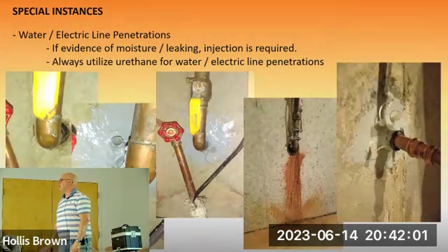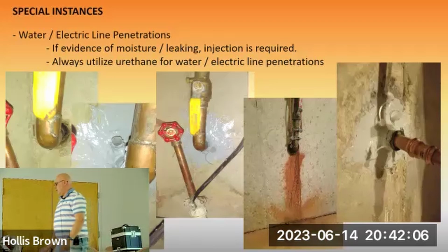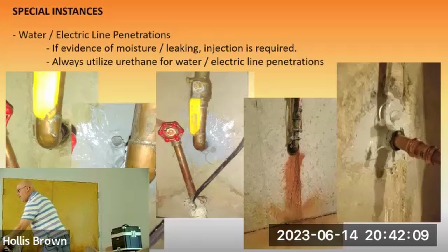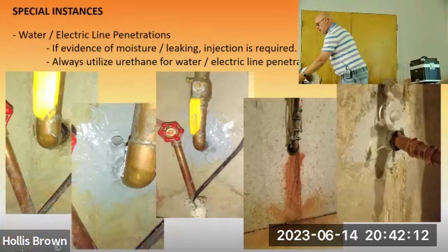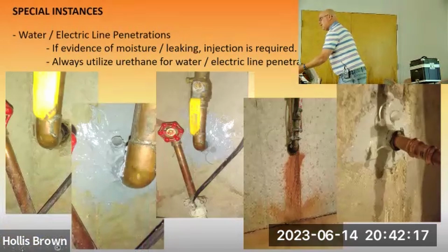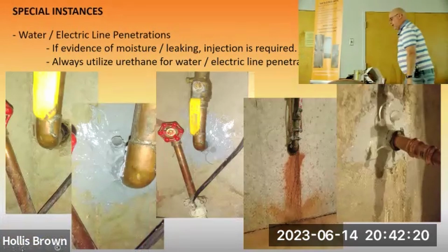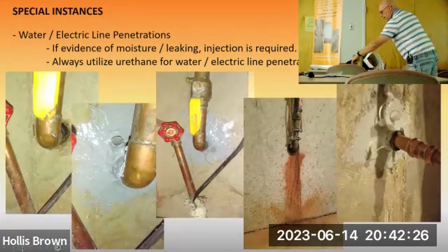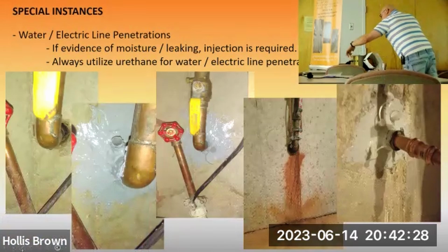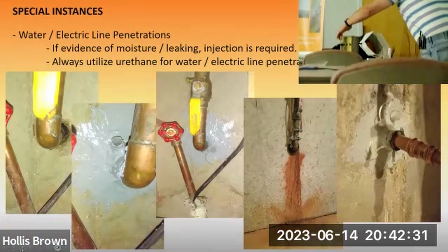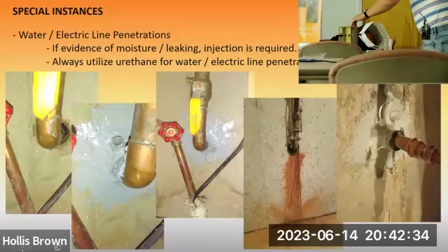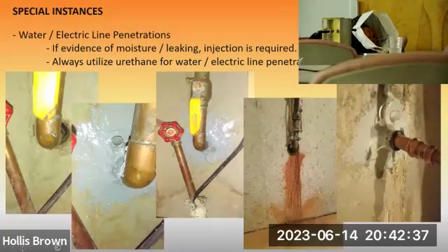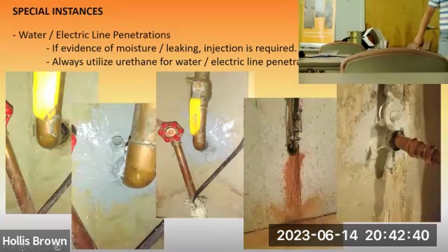How long between openings does it start to come up? Everything is perfect, you sealed in the back and on the ports. When I'm injecting this, if it's a very tight crack, it takes a little bit longer, but it could take anywhere from 2 or 3 seconds to start coming up, or it can take up to a minute. And if you're worried about it not penetrating all the way through, keep in mind it's already walked up here, and then I start injecting this more, so it's backfilling into there more and continues to fill up.